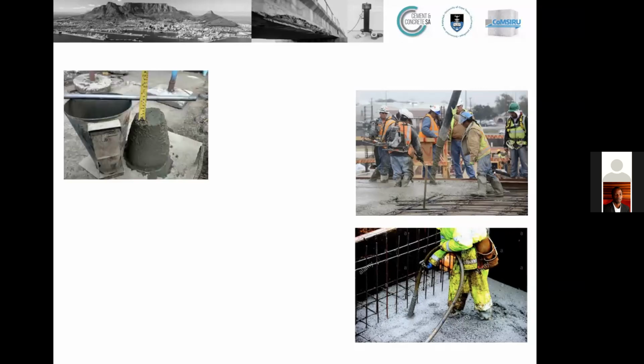And we define workability using the slump test, which of course has got nothing to do with any of those things that I just described. But we have accepted that there is a certain correlation which allows us to use the slump test as a simple indication of what we would expect in terms of workability, even though the test method as such doesn't really reflect on what we're actually wanting to identify.